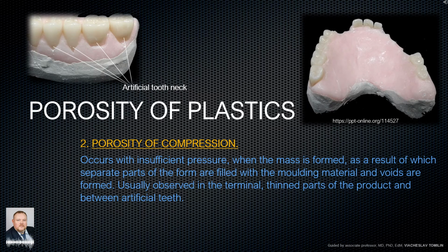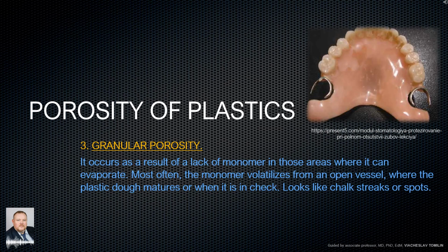Porosity of plastics. 2. Porosity of compression. Occurs with insufficient pressure, when the mass is formed, as a result of which separate parts of the form are not filled with the molding material and voids are formed, usually observed in the terminal, thin parts of the product and between artificial teeth. Porosity of plastics. 3. Granular porosity. It occurs as a result of a lack of monomer in those areas where it can evaporate. Most often, the monomer volatilizes from an open vessel, where the plastic dough matures, or when it is in the check. Looks like chalk streaks or spots.